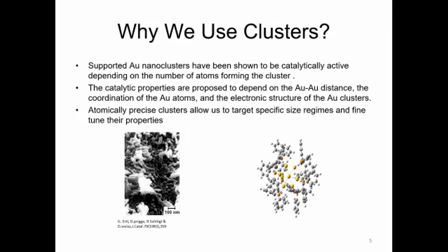Depending on the number of atoms inside the nanocluster, it can relate to different catalytic activities, like gold 9 is different than gold 8 and different than gold 11. But the previous literature used them in the gas phase, while to reach the demand of the industrial catalyst, we need to synthesize them chemically. And this is the difference between what has been reported in the literature in the gas phase and what we produce here: the catalytic activities for the cluster as chemically synthesized.